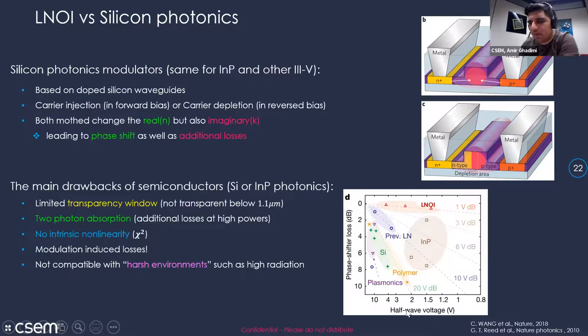So what you have to remember reading this plot is that we can always make the V-pi, or operating voltage, of these modulators lower and lower by going to longer and longer devices. But with longer devices, the extra losses become more apparent. So for example, look at silicon. If you want to make a modulator long enough to have a V-pi of 1 volt, you lose 20 dB of the light just in the modulator. And I'm not talking about waveguide losses. These are excess modulation losses.